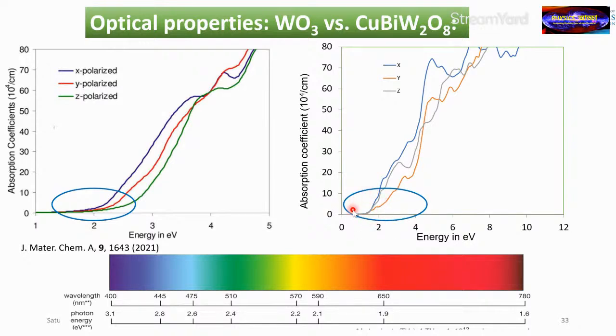So the goal of our work, to go from tungsten oxide to a new alloy, was kind of successful, because we now significantly absorb light at a lower energy. It started from around 1.6 electron volt, what we calculated, and if we start from 1.6, we're basically absorbing everything. Because if you go from 2 to 6 electron volt, this covers the whole range of the visible spectra up to some ultraviolet region. And as you can see, the light absorption probability increases as you go to the higher energy.